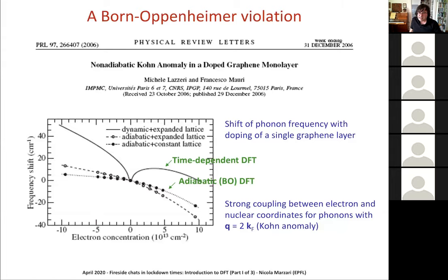Now, this adiabatic approximation is what we'll use for the entire tutorial, but let me give you a few examples where this approximation starts failing. This is actually a nice one. This is looking at something that you can measure very well. You can measure with Raman spectroscopy the vibrational frequency of certain phonons, in this case zone-center phonons in graphene. And what the calculation in different flavors would predict for those frequencies as a function of doping in the Born-Oppenheimer approximation